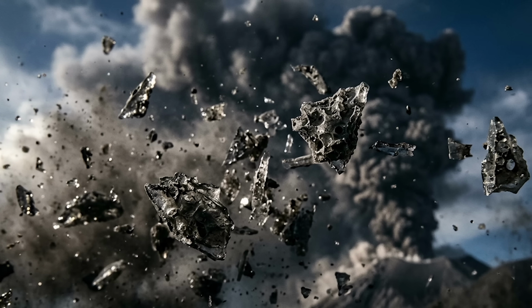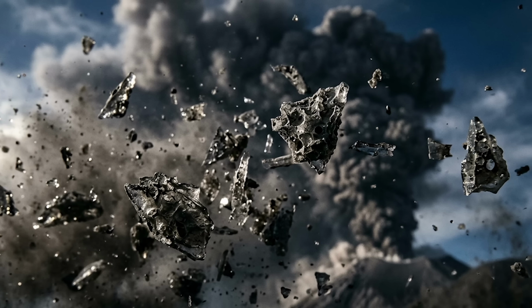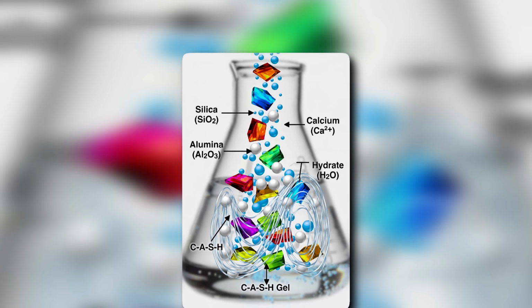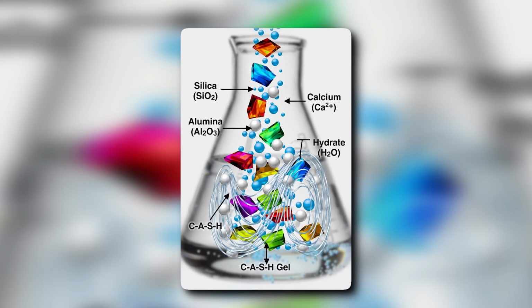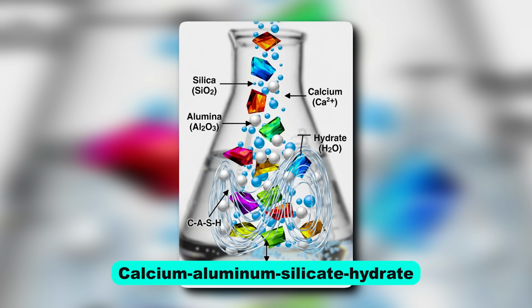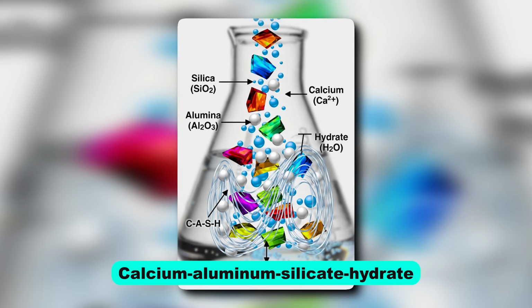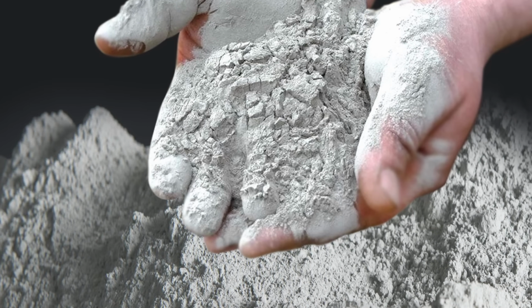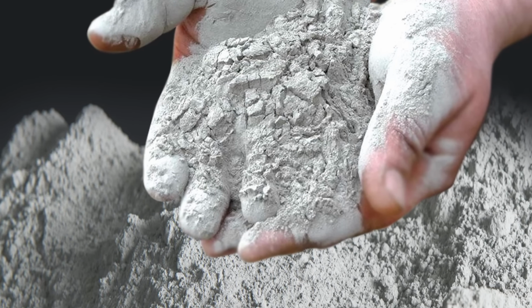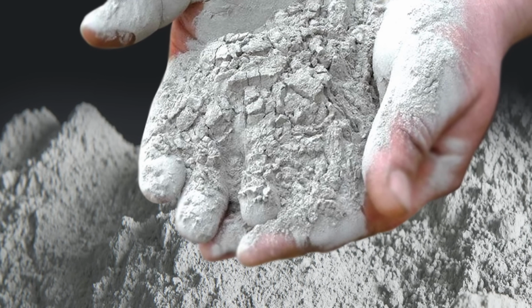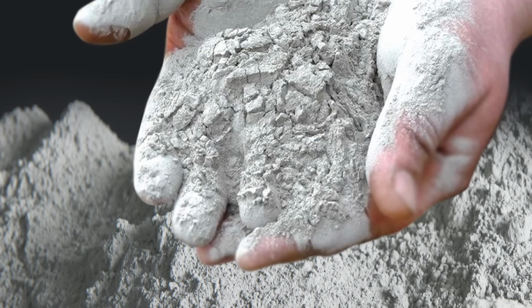Volcanic ash is glass, blasted into the atmosphere by an eruption full of reactive silica and alumina. Mix that glass powder with lime and water, and the silica and alumina bond into calcium aluminum silicate hydrate, a different mineral than what Portland cement forms, stronger, slower setting, self-healing.